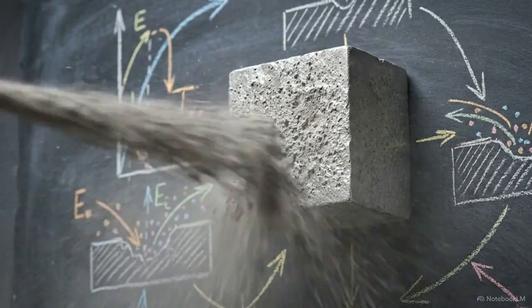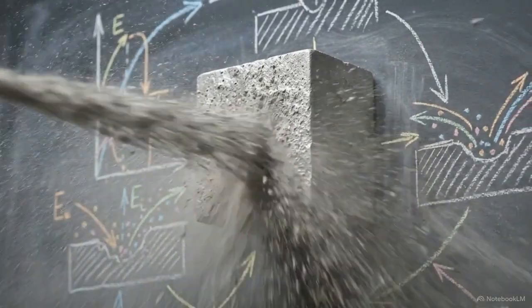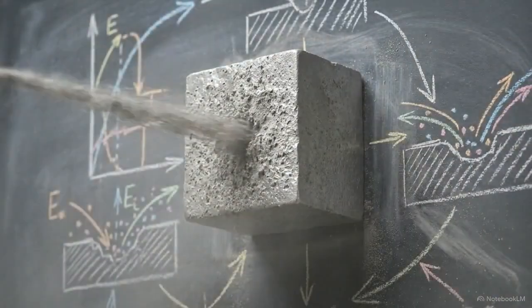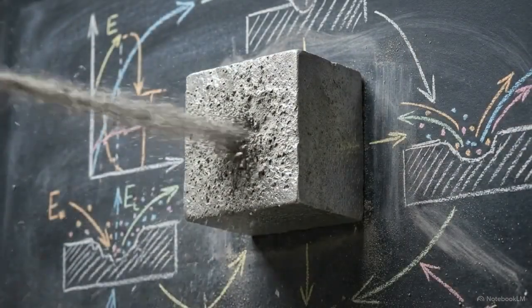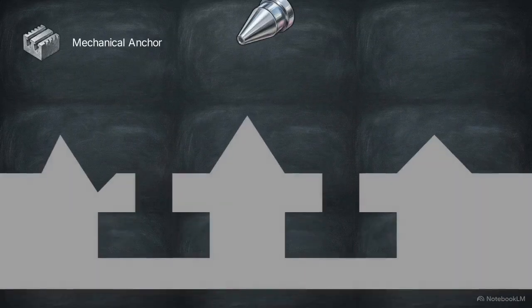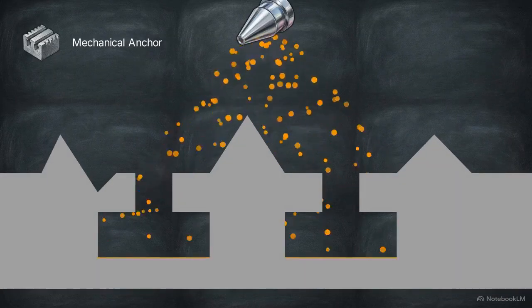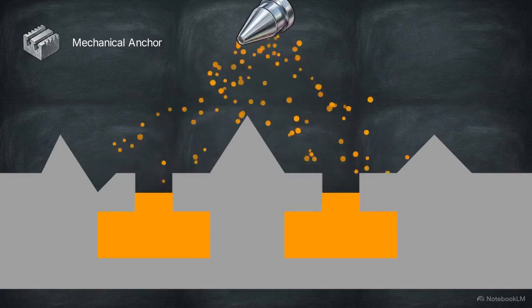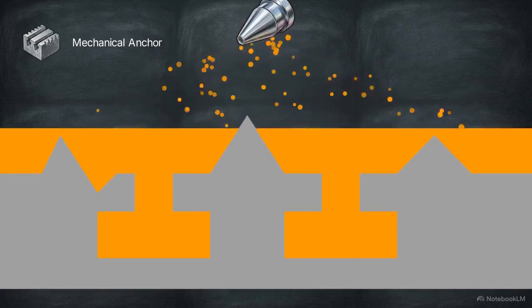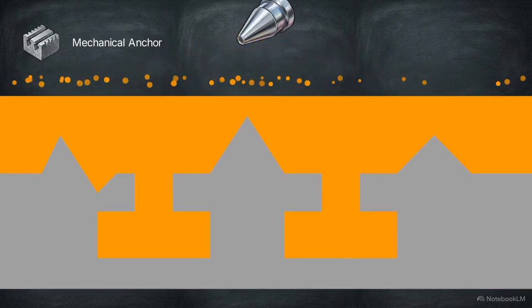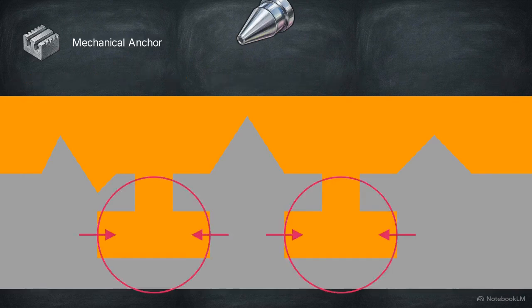PVD adhesion relies on chemical bonding at the interface and physical-mechanical interlocking. Engineers will often use abrasive sandblasting before the deposition process begins to increase the surface roughness of the base substrate. This artificially induced roughness provides microscopic crevices and valleys. As the vaporized atoms rain down, they fill these jagged features, creating an interlocking joint that reinforces the mechanical adhesion strength. Ceramic materials are also chosen for specific functions.